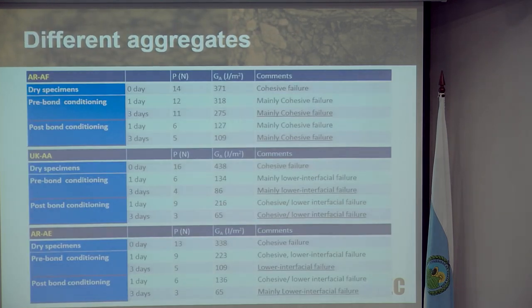Just quickly to summarize then, those are the three aggregates that I showed you. If you look at AE and AF, that's where you see the differences in terms of moisture damage, not because of the different mineralogies, but simply because they allow water to diffuse through them at very, very different rates.